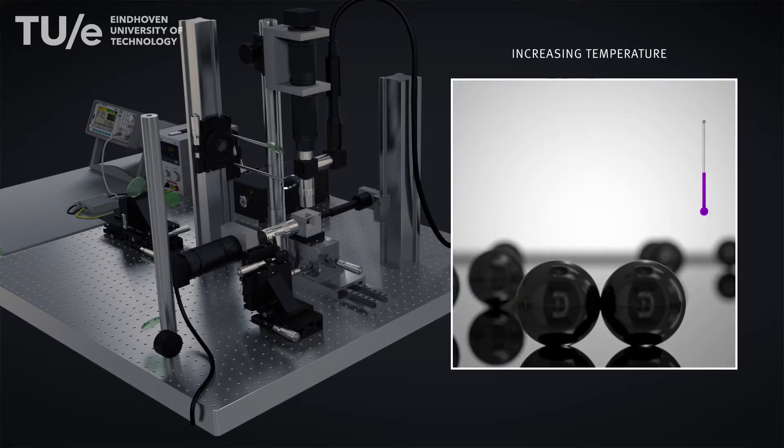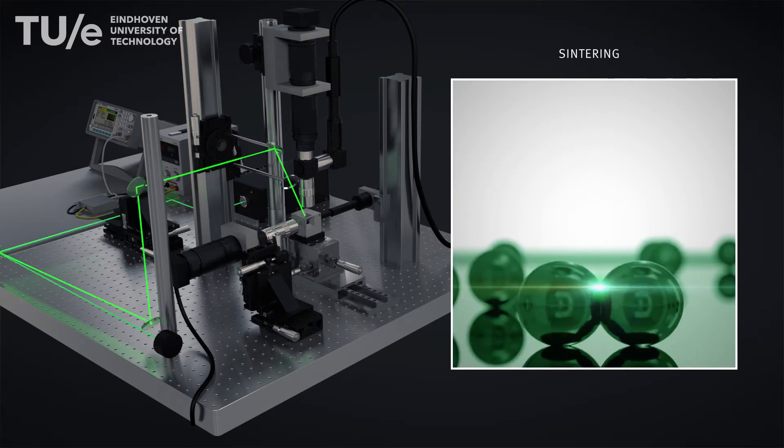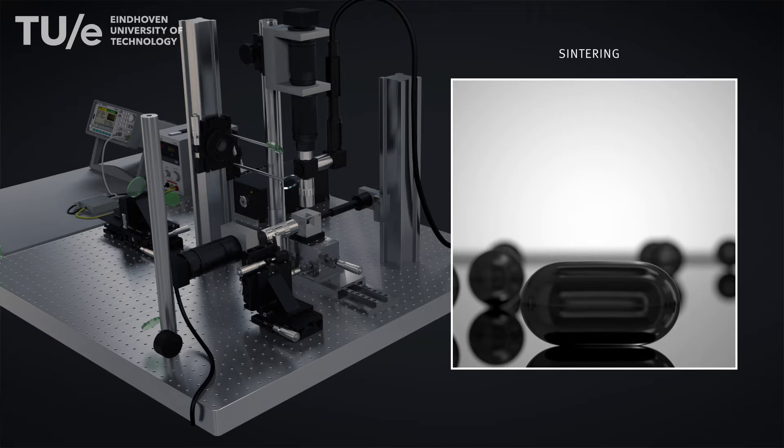To perform sintering experiments, the sample chamber is heated to the desired temperature. A single laser pulse of known energy is sent onto the particles, while the sintering process is optically visualised.